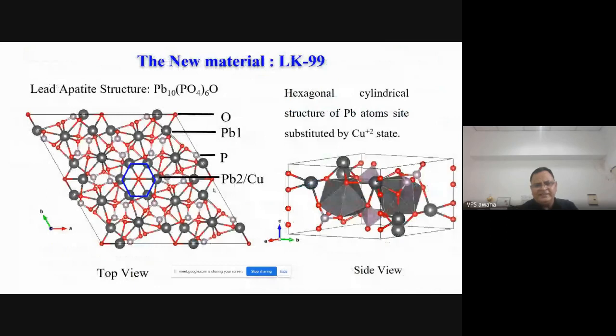And it was like this, that in this compound, there is a hexagonal of lead in the center of the molecule or compound, in a way. And there, if you replace the lead by copper, then you can have an internal chemical pressure in the system, which can lead to high TC superconductivity. And they did some calculations and all that also.